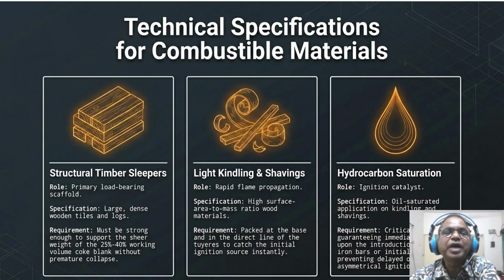The operational impact of this ignition catalyst is the guarantee of immediate lighting upon the introduction of first hot blast. So if you lack proper saturation, you risk asymmetrical ignition, where one side of the furnace stays cold while the other melts, leading to massive thermodynamic instability. So these materials are only as effective as the geometry in which they are stacked.